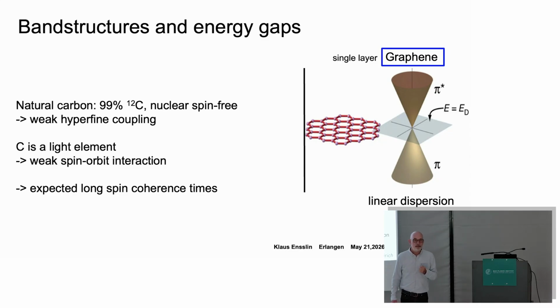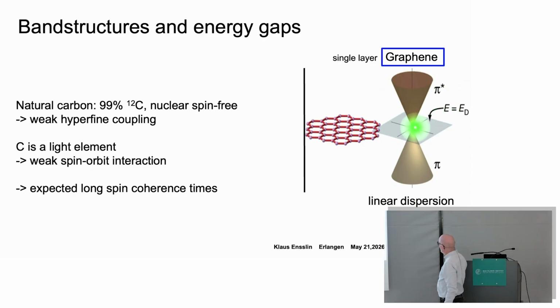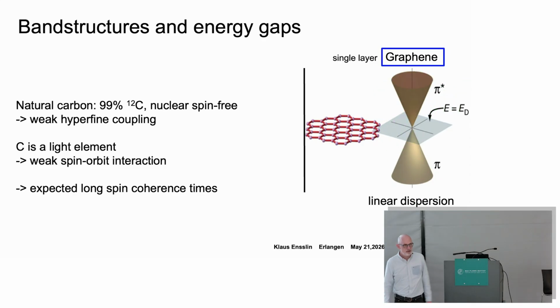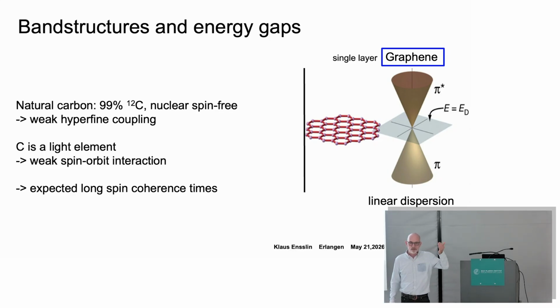And now you want to build a transistor. And you realize wherever you put your Fermi level in this band structure, there's a finite density of states. There is one particular point, the Dirac point, where presumably the density of states goes to 0, but obviously in reality it's not 0 because of interaction effects and all kinds of disorder. So you can never switch off this transistor because there's no band gap. So graphene is a bad material to start with to build something that confines electrons. So what do you do? You have no gap, no dot, no qubit.